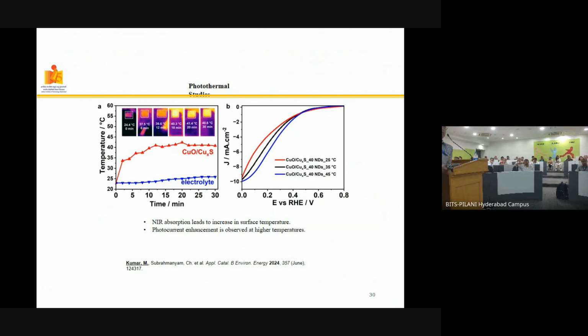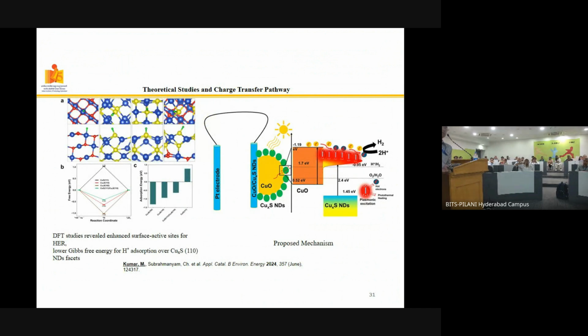That's where, in situ, you also have a little bit of temperature build-up. And you look at that, the current nearly remains the same, at least in all these cases. The photocurrent enhancement is also seen slightly at higher temperatures. So this was also done with the help of my colleague. I'm not an expert in these DFT calculations.